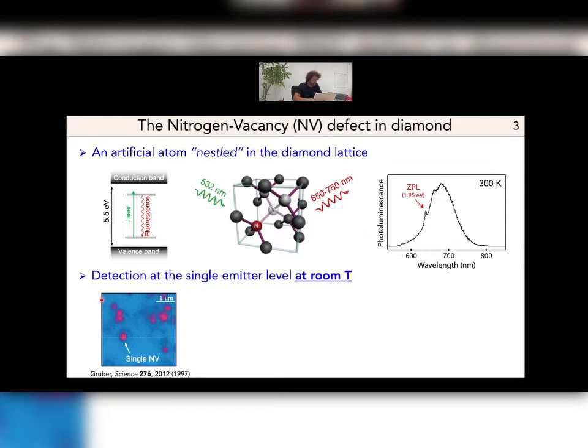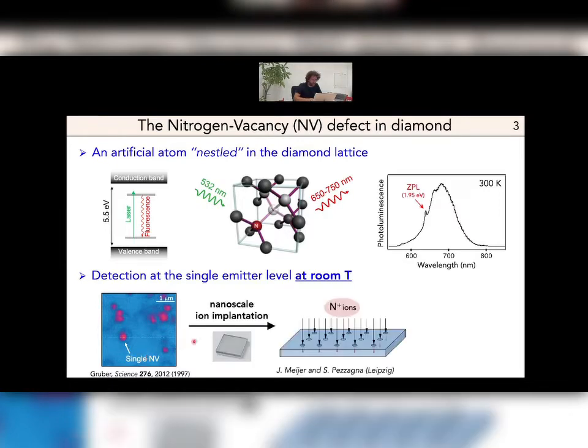So what you see here is a photoluminescence scan of a natural diamond sample, and the spots that you can see correspond to the emission of photons by single NV defects in diamond. Since that time, there have been a lot of efforts to try to control the creation of this defect in diamond, and a promising solution is to use nanoscale ion implantation.